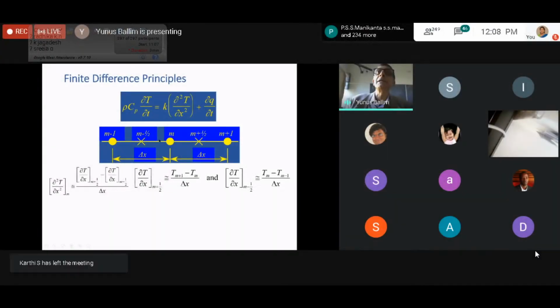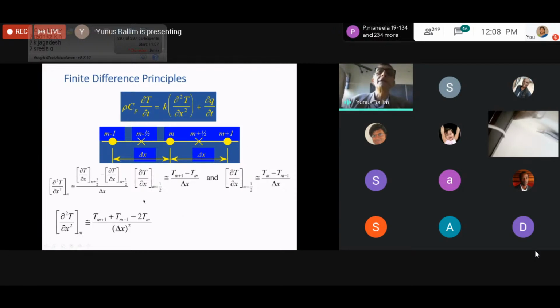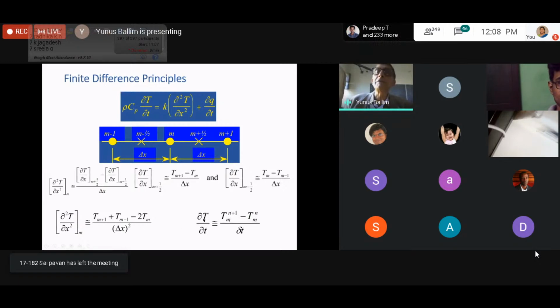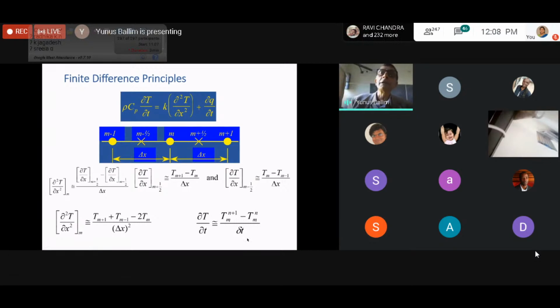The first order differentials are determined by the temperature difference between that point and that point, and similarly that point and that point. And from there you can get a second order differential that is based on the temperature at M, the temperature at M minus 1 and the temperature at M plus 1 divided by delta x squared. Okay? And then of course you can approximate the time differential as the temperature at point M in time interval N and at point M in time interval N plus 1. So I'm doing a forward step calculation, divided of course by delta T, whatever delta T we choose in the model. It's a forward step calculation, and that essentially is the principle for developing the equations.